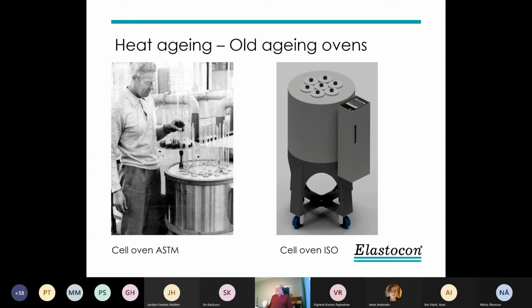If we look at the ovens which have been used for testing of rubber, the one to the left is a cell oven, still specified in ASTM. I think people understood quite early that you needed a very stable temperature and you needed to separate the samples. That's why a big aluminium block was used and separate test tubes for each material. The small tubes in the picture there was an idea that you need to change the air to keep the oxygen concentration constant. But it's not possible to measure how much you change the air in that setup.